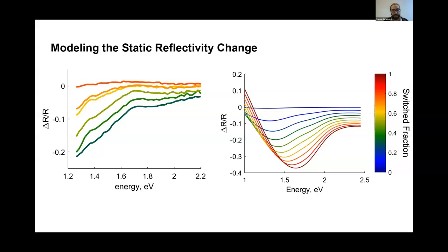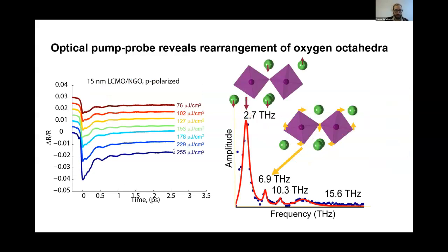So if the terahertz spectroscopy tells you that about half your material is in the insulating phase and half is in the conducting phase, qualitatively and somewhat quantitatively, and I'll get to that later, the optical reflectivity data agrees with this. So now, what is happening upon photoexcitation? What's happening in those first few picoseconds?